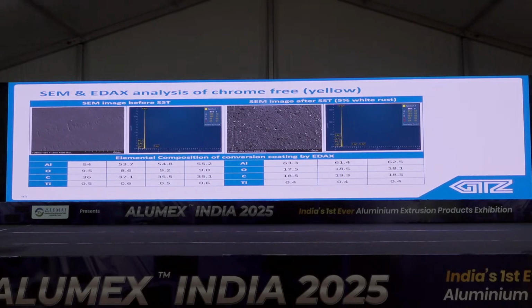This first slide is the same picture and EDS spectrum of Foam 3 yellow before SST, and the right one is the same picture and EDS spectrum of Foam 3 yellow after salt spray, that is 5% white rust. Here also the main components of Foam 3 yellow are organic and titanium. Before salt spray, you can find the higher content of carbon as well as titanium. After salt spray, both carbon, that is the representative of organic chemical, is also getting reduced, and titanium also reduced.